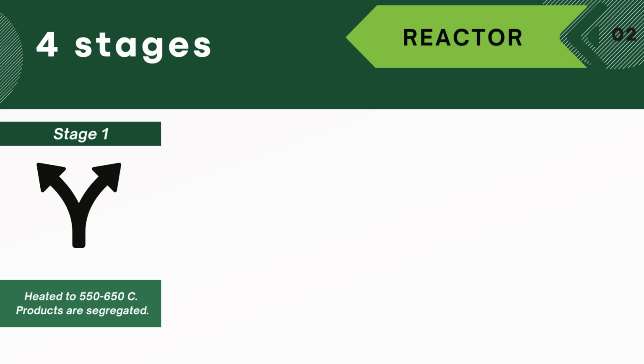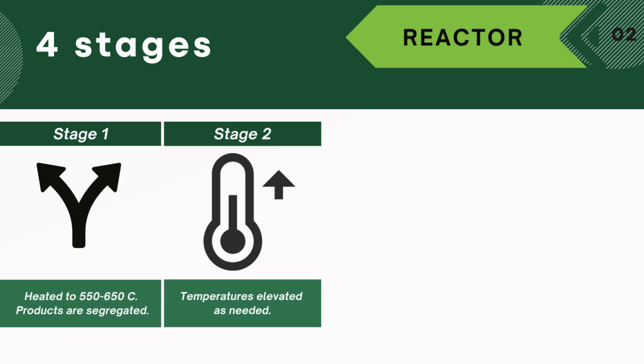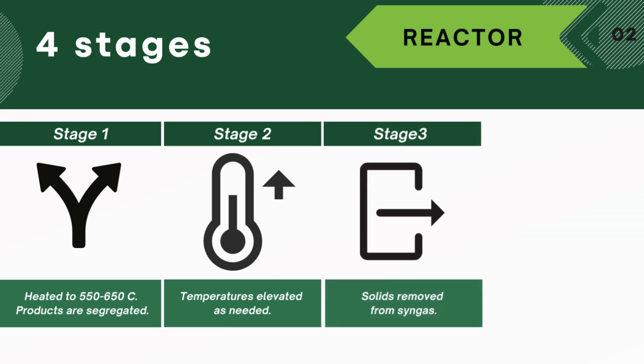The first stage products are segregated into 2 streams, a second stage dusty gaseous stream and a third stage solid stream. Dust and particulate matter are captured and removed between the first and second stages. The second stage gaseous stream is passed to the second stage steam reforming kiln that elevates the reforming temperature to 850 to 1100 degrees Celsius, or higher if necessary to complete the reaction. This second stage facilitates the complete conversion of the carbonaceous gases to a syngas consisting primarily of hydrogen, H2, and carbon monoxide, CO. The third stage further processes and removes solid materials from the raw syngas.